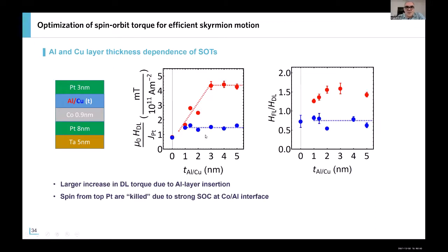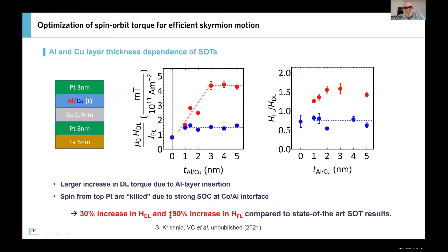And this is proved also by this thickness dependence for the two systems. You see that we almost have no thickness dependence for the copper, whereas there is a strong increase of the damping-like and of the field-like torque in the case of aluminum. So this is a signature of a combination of two effects from the aluminum. First, as I said, this Rashba contribution, but also the fact that for a thick enough aluminum layer, basically we kill the spin current that is generated in the top platinum layer, which could act with opposite effect on the cobalt. So to summarize, by doing all these precise measurements, we demonstrate a large increase of both the damping-like torque and the field-like torque compared to the state of the art.